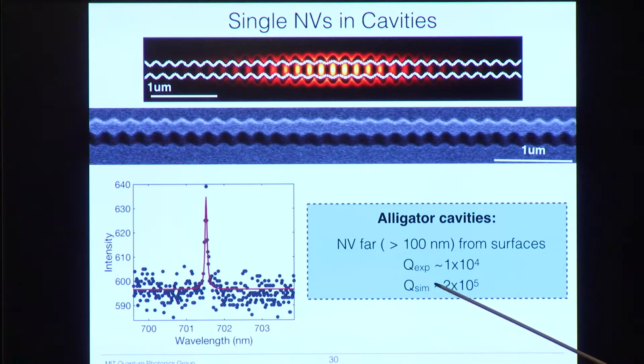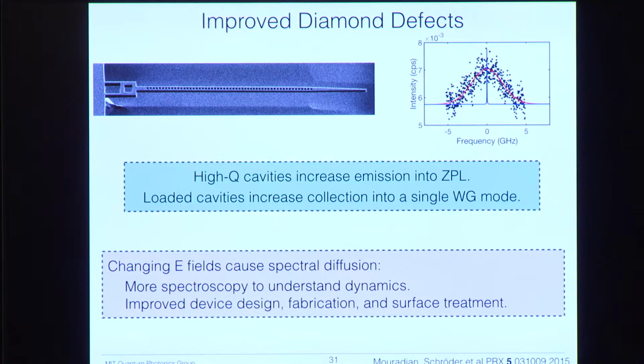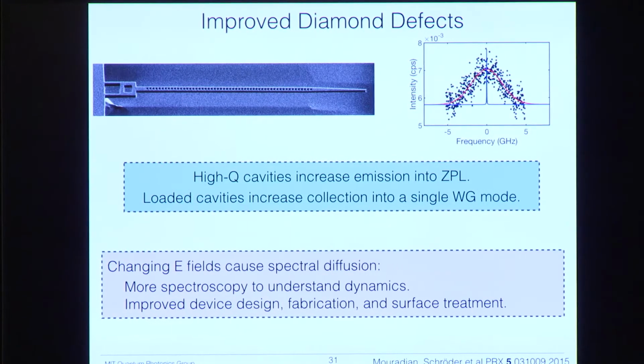And also in simulation, we can get quite high Qs, so around 10 to the 5th. And so we fabricated these and measured them, and we can see that we get Qs around 10,000. This was the first fabrication run, so it seems like it has good possibilities for the future. Unfortunately, I didn't get around to doing this in diamond with single NVs, but we hope that this will give us both the line widths of waveguides plus the high Qs of a high Q cavity. Yeah.